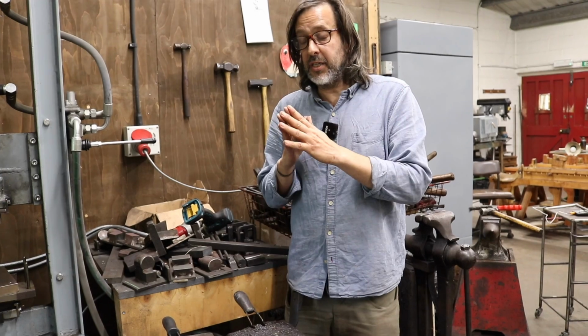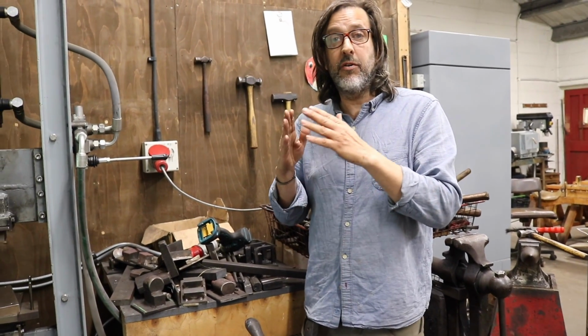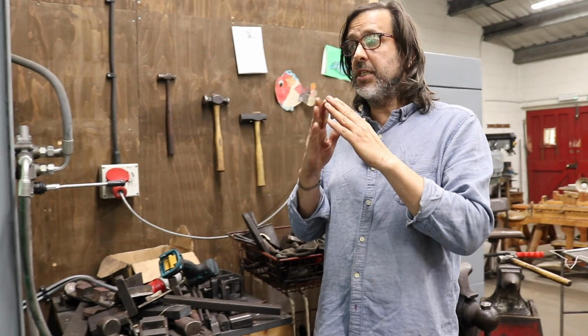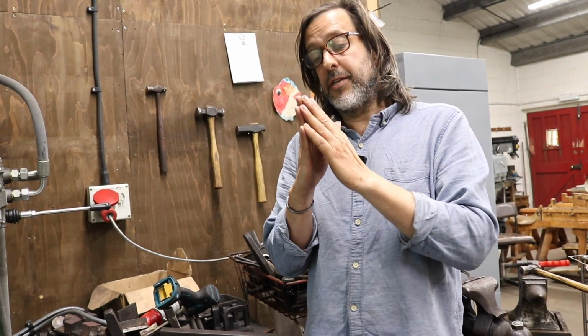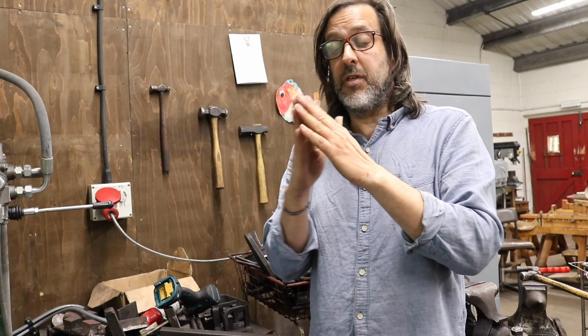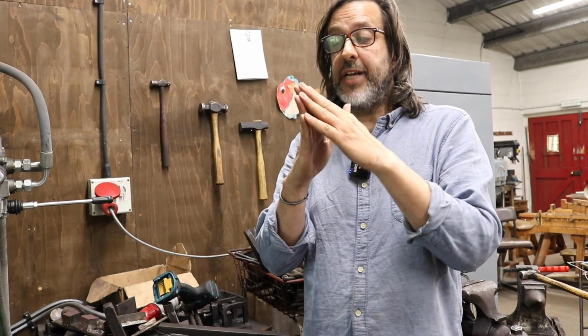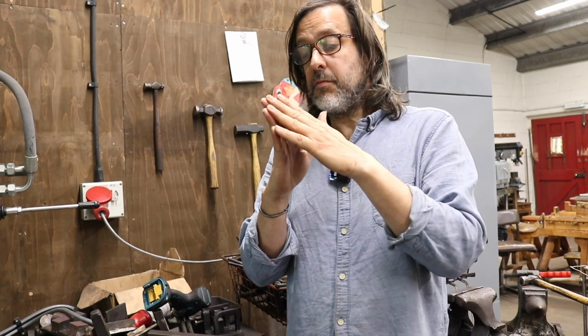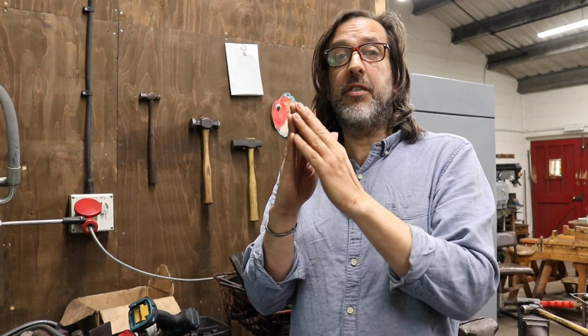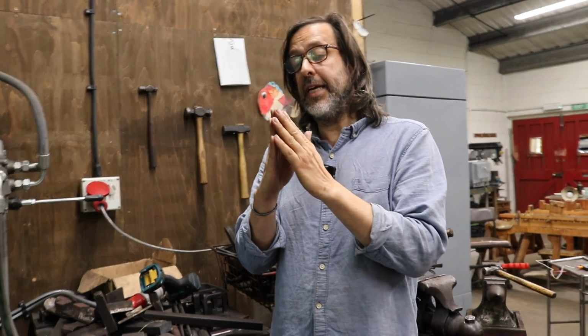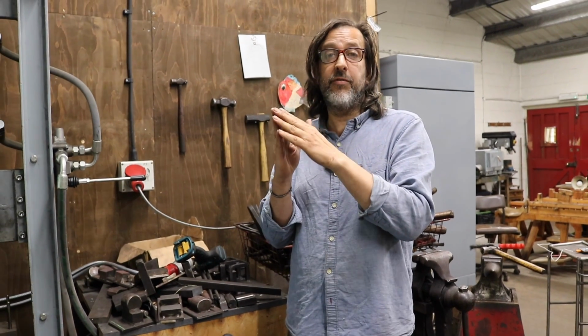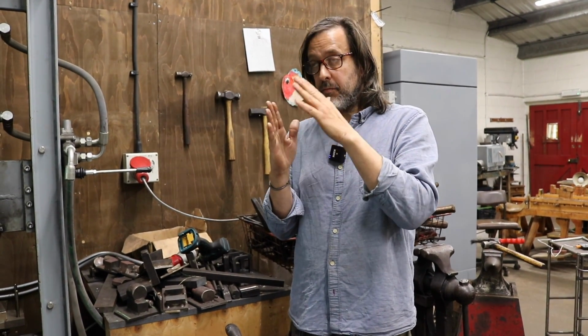If you make an edge from fully hardened steel with no tempering, the danger is that when the edge hits something hard, like a knot, it flexes, because at a certain point you put enough pressure on any steel, the edge is going to move. If it's hard, it'll just chip. You'll get a little crescent, and it will deflect and it will snap. If you haven't hardened it, the edge will deflect and it won't spring back, it will deform, and that's a rolled edge. So edges will roll or chip. If you temper it, ideally it will flex, and it's softened enough, but it will come back to shape, and so you won't damage it.